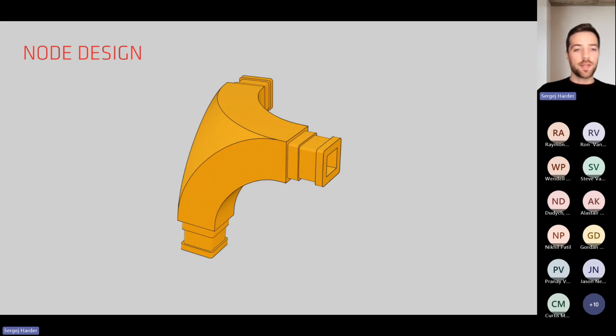So this is how the node looks like. And this is optimized for adhesive bonding. It's a hollow structure inside, so it's also possible to pass cables through these nodes. Then you have this recess for the centering of the square hollow structure that you put on top of these nodes, and it automatically centers this square hollow structure. On top, you have this joining channel where you apply the adhesive. This can be manually pumpable, for example, also for a robotic application. And then on the bottom side, I will show in a second, you have, for visual confirmation, two ventilation holes where you see if your adhesive completely passed this gap for the adhesive to act.